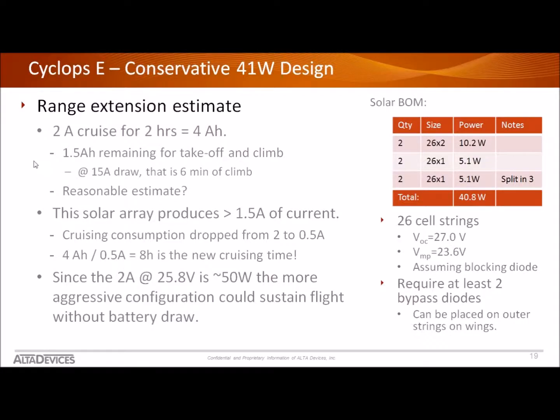So picking relatively conservative numbers of saying an amp and a half means that we would take our cruising consumption of 2 amps and drop it down to about half an amp of draw from the battery. Now, with that 4 amp hours of battery capacity, and we divide that by the half an amp, you get about an 8-hour cruising time. So we've gone from a 2-hour operation time to 8 hours by adding solar to this solution. Now, at 2 amp draw and the full battery potential, we see that's about 50 watts of power.